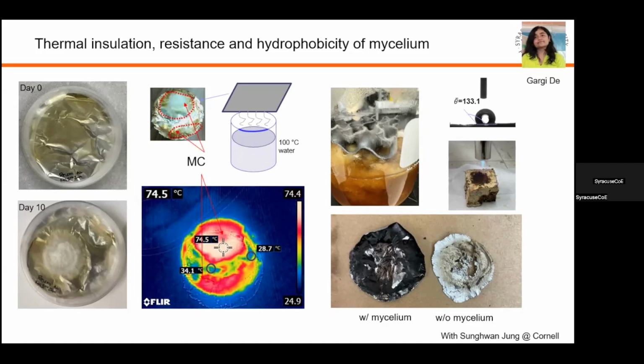We also show that the mycelium can coat other 3D structures. So we put the 3D printed structure in mycelium, and then they can also grow over time. This is hydrophobic, so this water contact angle shows a hydrophobic surface, and it is also tolerant to fire and temperature. This image shows what happens once you directly test under the flame the aluminum foil coated with mycelium and not coated with mycelium.